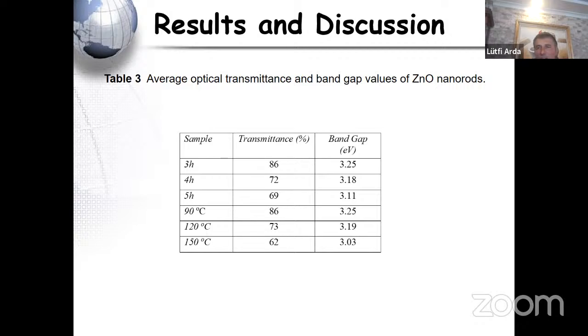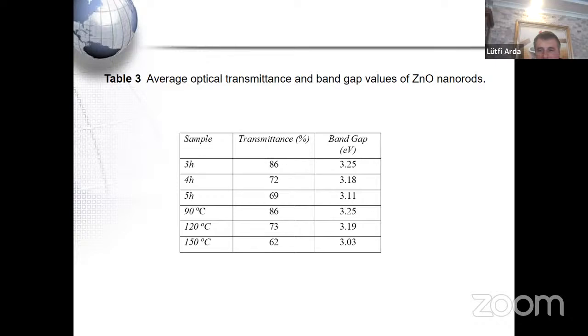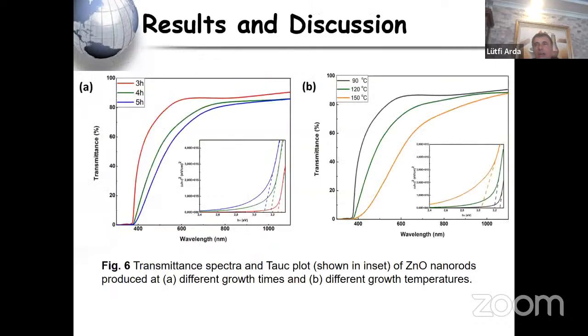studies. According to these 2 figures here, for the sample grown at 90 degrees, the average optical transmittance in the visible region is about 86%, which decreased to about 62% as the growth temperature increased to 150 degrees.